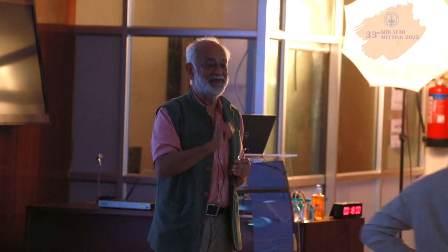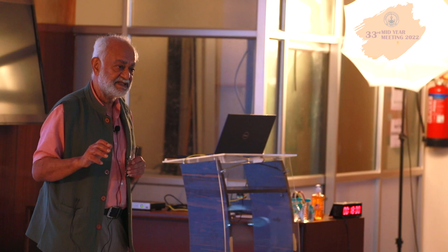So it's this reversibility that drives the shape memory. It's a little more complicated than that, because not all materials which show martensite show the shape memory effect. When the parent phase forms, it has to revert back exactly along the same path that the martensite formed. It's only then that you revert back to the original shape.